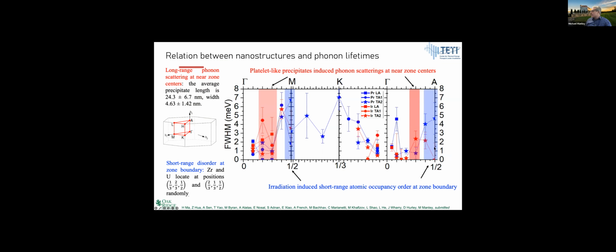The zone boundaries, we think that as you start to form these precipitates, you're also cleaning out some of the short range disorder that may be affecting some of these very short wavelength phonons. And of course, the long wavelength phonons are maybe not seeing it just because they're much longer than the size of these things.